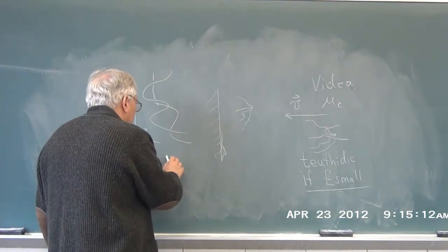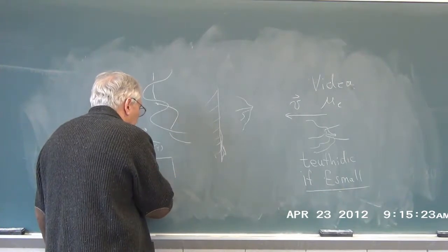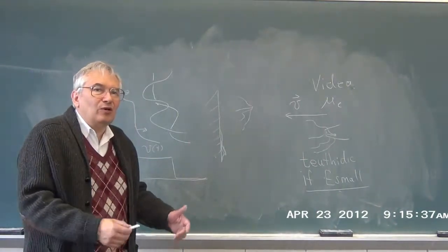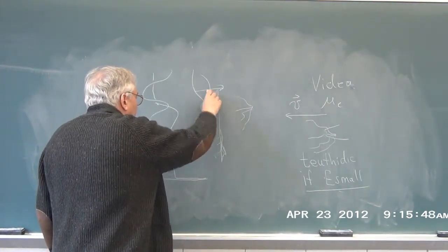Well, the question is, what happens next if this chain tries to move that way some more? And one answer is, if I plot V versus time of the two chains, we have the moving chain, which is chugging along, and it reaches the chain that was sitting there, and the two chains then come to a stop because one chain keeps the other from moving due to the excluded volume force. The other, which is the interaction seen, say, in a rugby scrum or an American football game, is this chain is moving, and it encounters the second chain, and they get dragged along, and therefore the second chain is dragged along by the first.